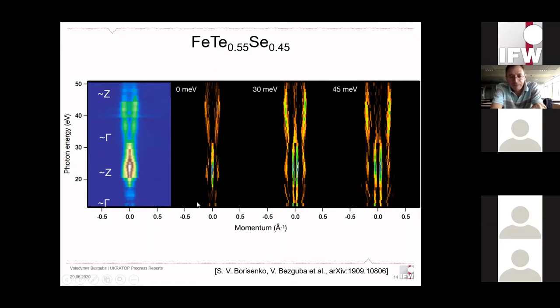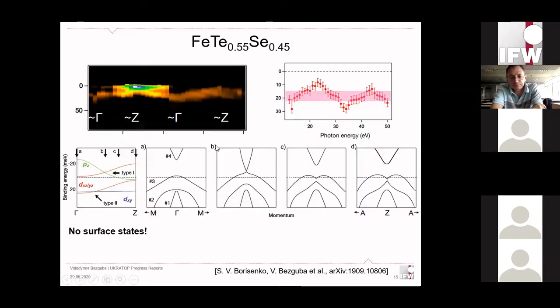So there are no signs of topological surface states. If we do the cut, these 3 cuts, these 3 pictures, they are second derivatives of this, but at different levels, the Fermi level and slightly lower. And if we do the cut of this and look at how it disperses over kz, we see that there is one band which looks like dxz, dyz, and another band coming closely in around the Z point, which almost touches the dxz, dyz and then comes back up. So after analyzing all of the data and summing up all of the results, we came to the conclusion that there is no topological, no inverted gap here.